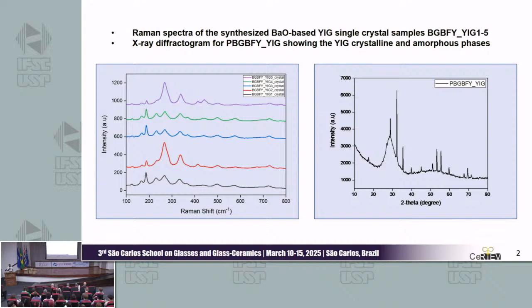So I investigated how varying yttrium oxide and iron oxide doping concentration affects the crystallization, microstructure, and optical properties of yttrium iron garnet crystal. When you look at the Raman spectroscopy and XRD, it confirmed the successful nucleation and crystal growth of this material within the glass matrix. Also, the Raman spectroscopy shows varying peak intensity at around 188 and 267. This is due to a possible correlation between the crystal environment and composition.